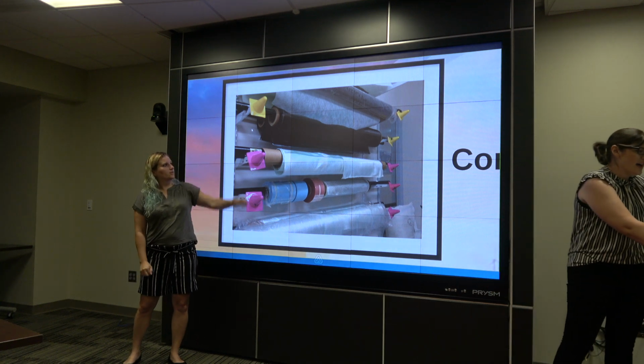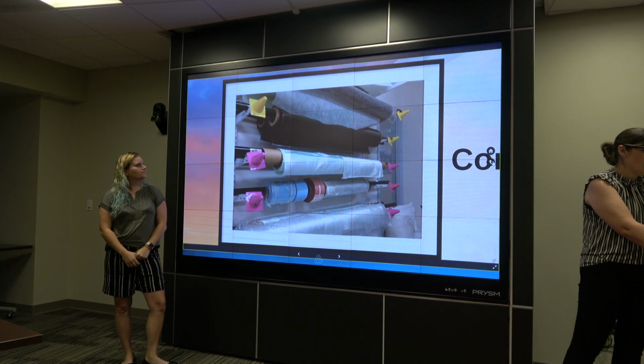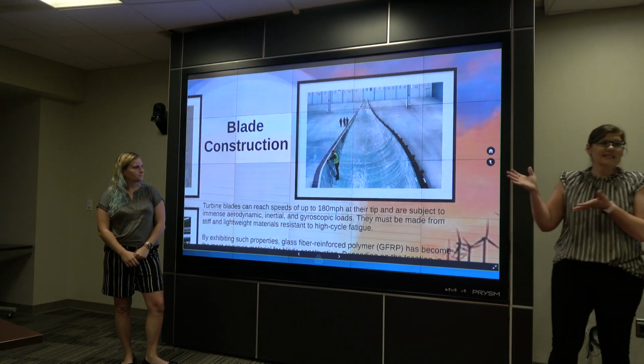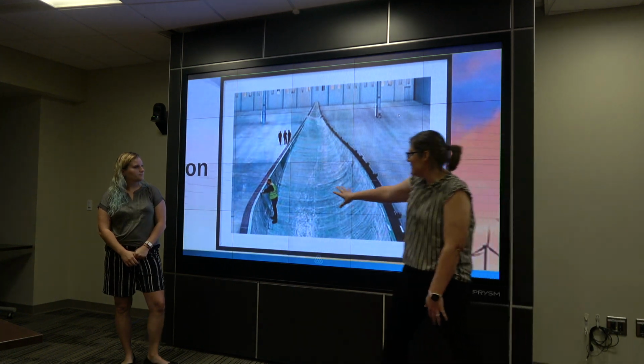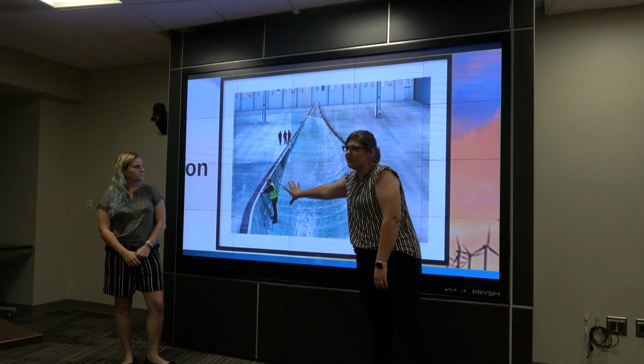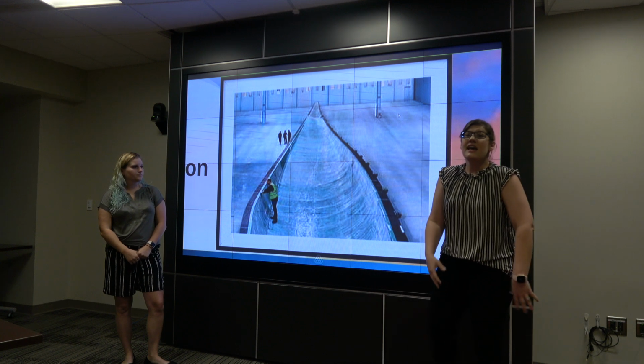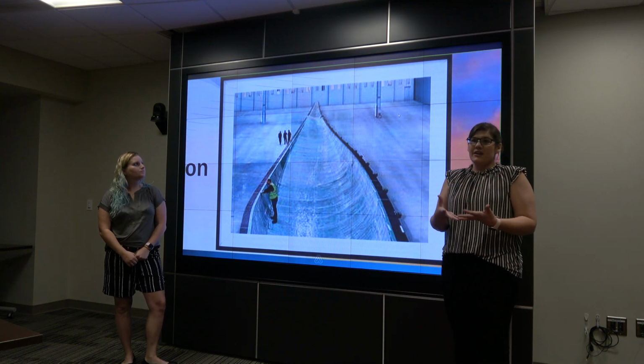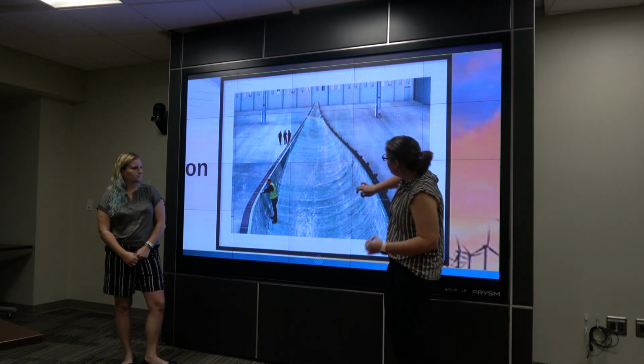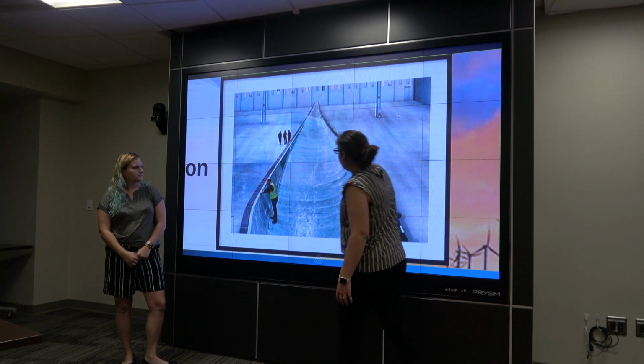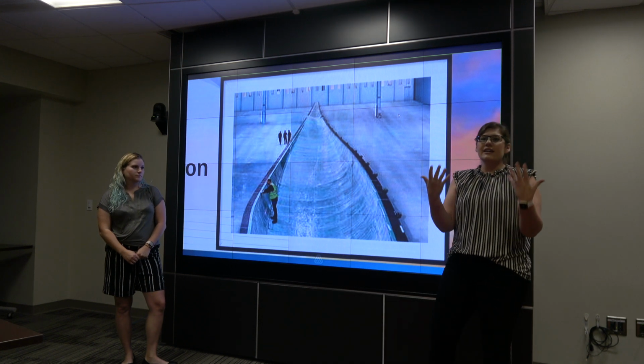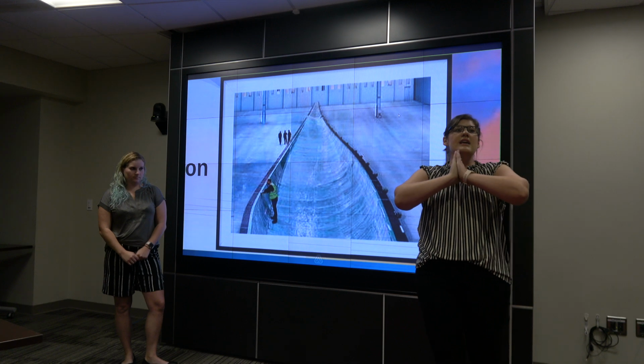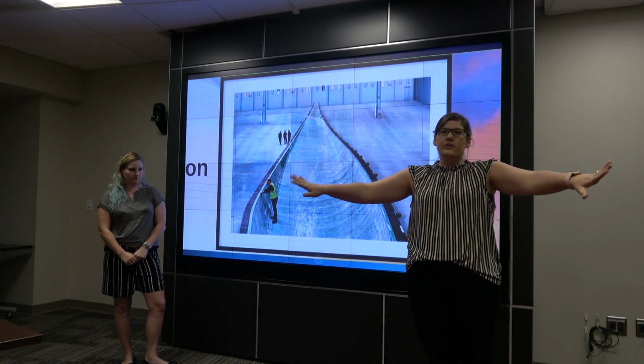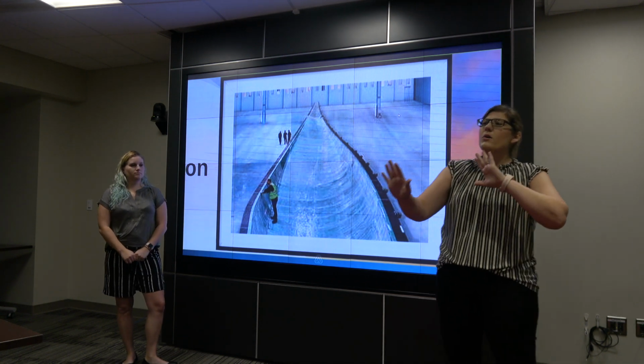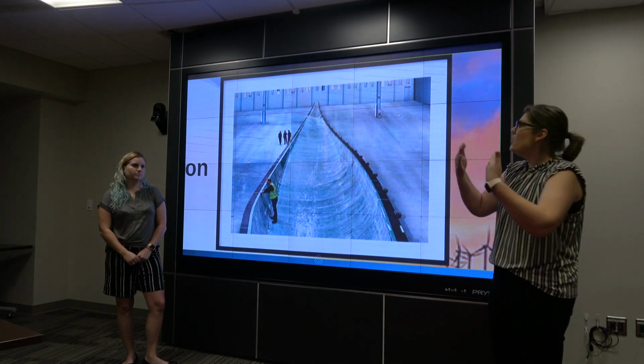So when they do that, it's just unreal to me, because this is a wind turbine blade. You can see the size comparison, the guy standing down inside the blade to construct that. They also use a vacuum, okay? So they have just tubes all along here, and they do the vacuum layup, and they're sucking out the extra resin. They're making sure that the resin permeates all of the material equally so that there's no weak spots or spots with too much resin throughout the blade.